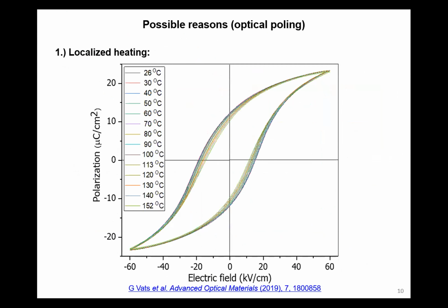Yeah. So could you confirm the phase transition temperature? I mean the structural phase transition temperature for this material? The structural phase transition was above 400, and there is an anomaly at around 170 degrees centigrade. So this P loop is below any structural phase transition. Yes, yes. Okay. Thank you.